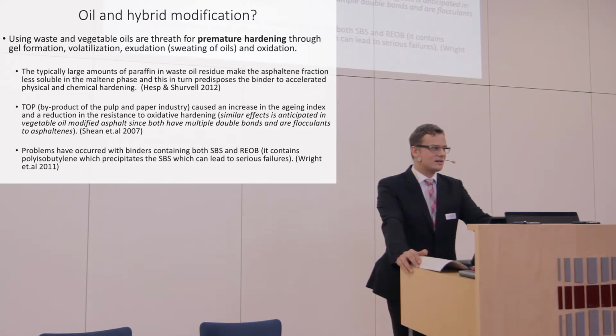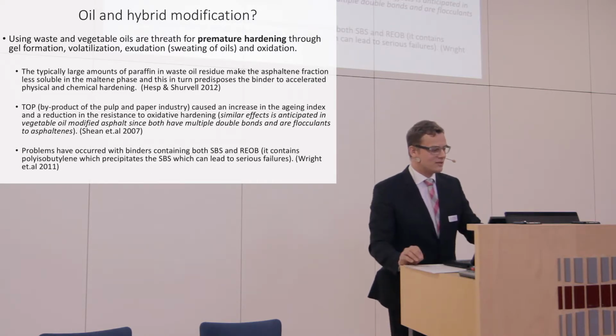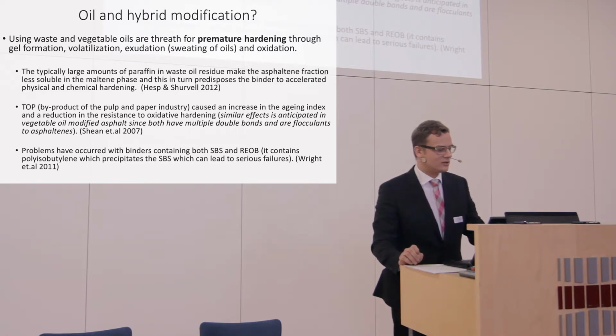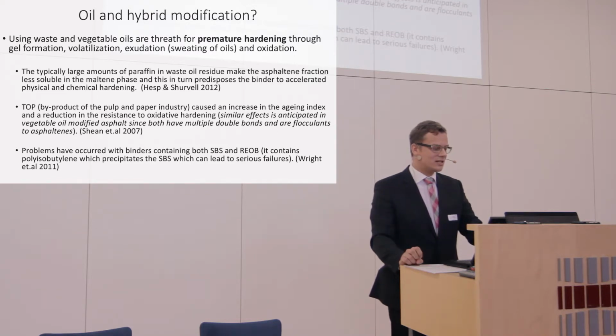Mikla asked, as you asked from Bahia about this also, what happens if you modify your bitumen with oil? And that's a very good question, because in the literature we can see that using waste and vegetable oils, they are a threat for premature hardening through gel formation, volatilization, exudation - that means sweating of oils - and oxidation.